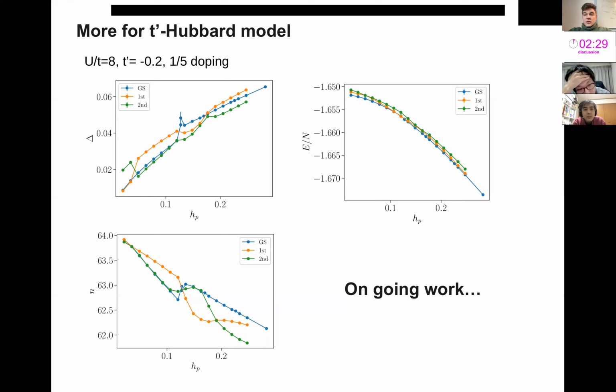So there has been a work by Stoudenmire. They used an algorithm called METTS, an algorithm combining the tensor network and Monte Carlo, to try to address this finite temperature issue. But the problem is that most of these finite temperature methods start from the infinite temperature, and they try to lower the temperature to the ground state. And for the lower temperature, the required bond dimension would be larger.